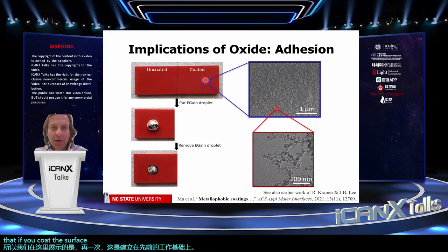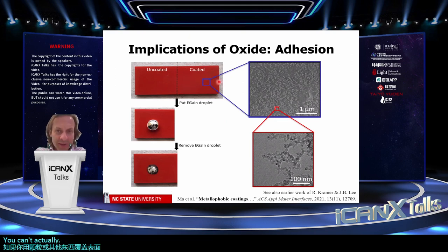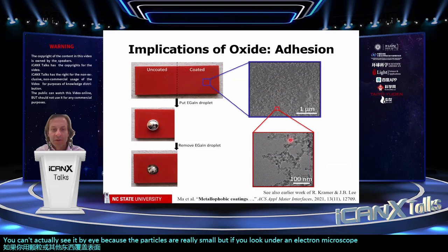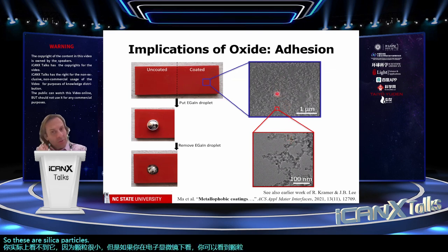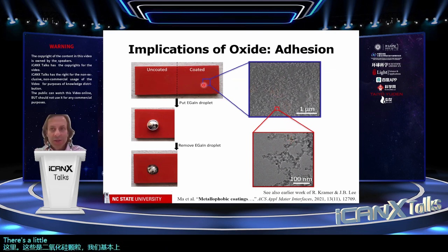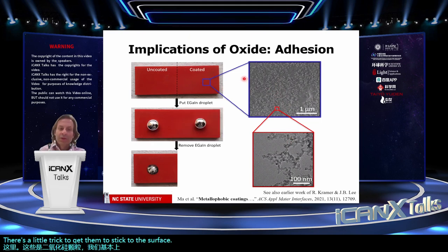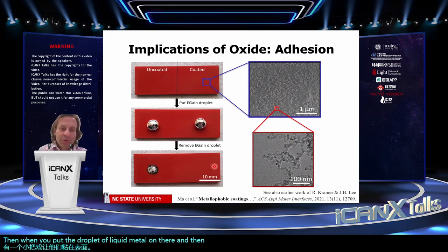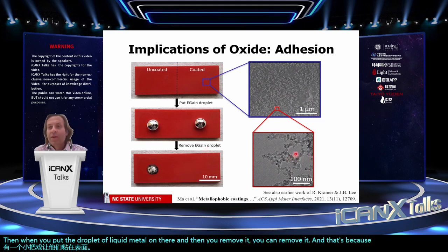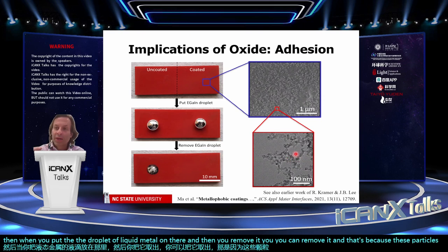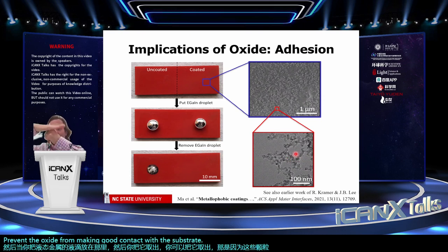you can't actually see it by eye because the particles are really small. But if you look under an electron microscope, you can see the particles here. So these are silica particles, which we basically, there's a little trick to get them to stick to the surface. Then when you put the droplet of liquid metal on there and then you remove it, you can remove it. And that's because these particles prevent the oxide from making good contact with the substrate. Basically, they keep the oxide from making contact.